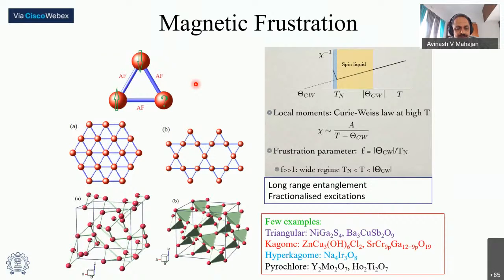And then what does happen when these are there in an actual real material? That has been an interesting question. So this was stated by Anderson long ago. And the RVB state has perhaps its origins in this kind of frustration. Eventually it turns out that the edge-shared triangular lattice appears to have ordered 120-degree oriented spins as the ground state. However, there is still interest in these various triangular systems because you might have other important interactions also, which prevent this kind of 120-degree ordering.